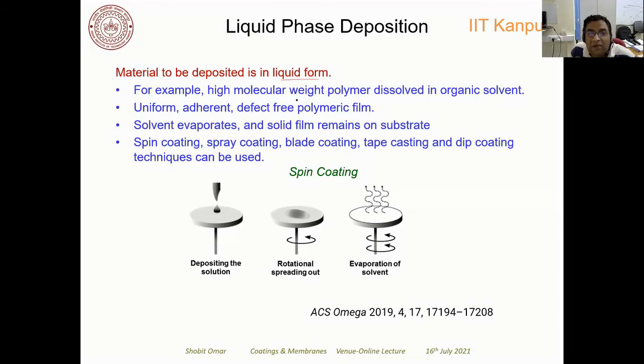Okay, so high molecular weight polymer is dissolved in organic solvent, and you will get a uniform adherent defect-free polymeric film using these techniques. And solvent evaporates, so you will evaporate the solvent, and the solid film that remains will form a uniform coating on the substrate. So there are various types of techniques present, and a few of them are listed here. One is spin coating, spray coating, blade coating, tape casting, and dip coating techniques.